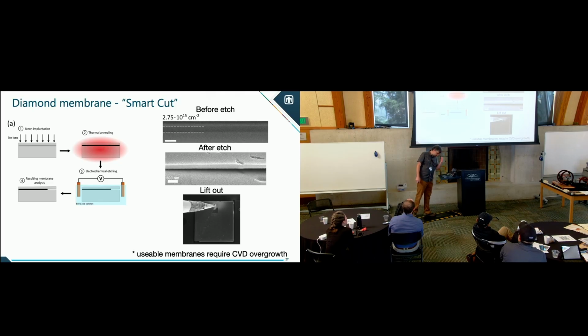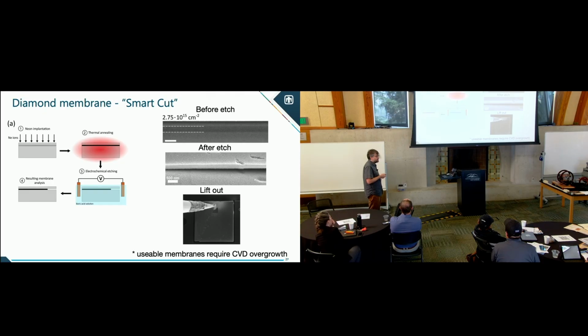This is a smart cut technology, and this comes back to how diamond is metastable. So diamond doesn't like to be in the diamond form at ambient conditions. So what you can do is a really high fluence implantation, and the stopping range of ion implantation in a material is kind of like a Gaussian at some depth. If you do a high fluence, you get this Gaussian-like region, some depth under the material proportional to the energy, and that turns into sp2-like carbon, which is more graphite-like. And you still have diamond on top of that. You can then anneal it and electrochemically etch that sp2 carbon away, and it releases this diamond membrane.